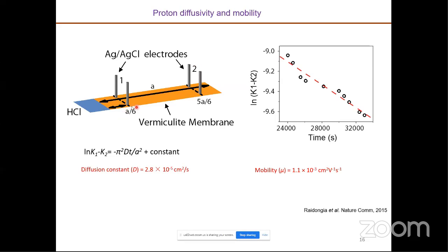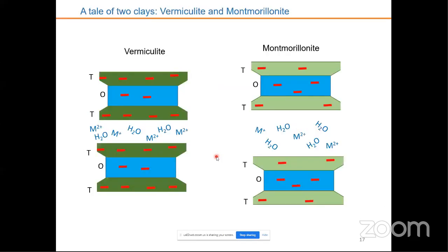The time it takes to travel from 1 to 2 can be measured by measuring the conductivity, and we can find out exactly what the speed of the ions through our channel is. These are very important parameters, and we can find that they are very different from bulk water. So it's very interesting to know this phenomenon, this kind of science in small channels, by using clay membranes.